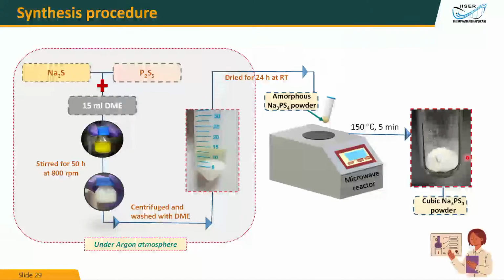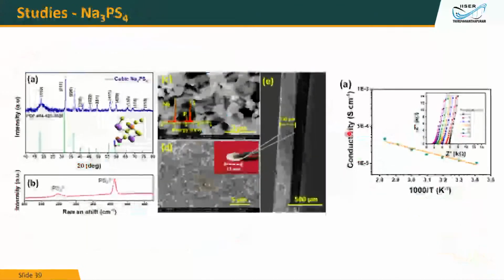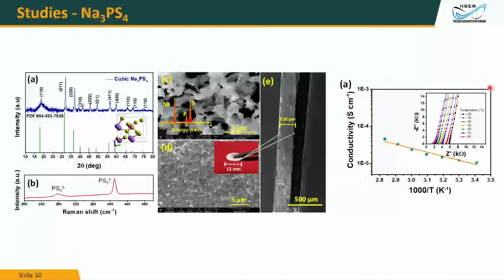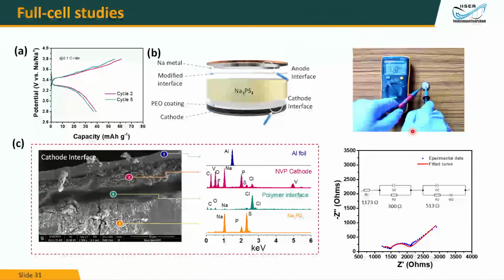We did not have solvent in it, so this is a dry approach compared to the conventional microwave research that we do, and in 5 minutes we were able to get this solid powder. And then we did a little bit of characterization. We were able to look at its conductivity, and then a little bit of cycling. We will have to work on the cycling. Here, in order to improve the interface, we used a polymeric membrane. So this is a cathode, this is the electrolyte, and we also have a polymeric membrane in between, so as to give a proper contact and a proper interface. We are still working on thinning down this interface and looking at a better cycling performance.